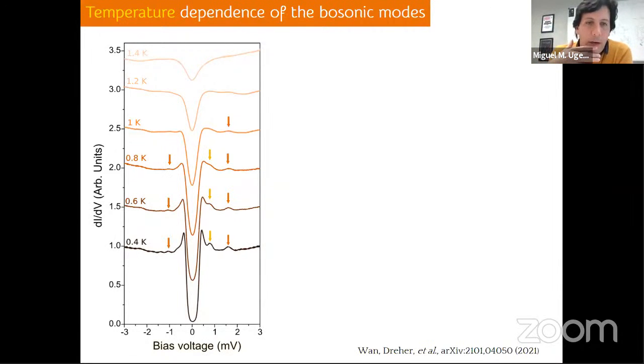So in order to learn more about the origin of these spin resonances, we have studied both the temperature dependence of these bosonic modes and the magnetic field dependence of the bosonic modes. Here I show you one typical set, increasing the temperature from our base temperature of 400 millikelvin up to 1.4 Kelvin. You can see here at very low temperatures, we can distinguish 3 different bosonic modes: the fundamental mode, which is here, and some replicas here and here. As you see, as we increase the temperature, still inside the critical temperature, these bosonic features decay. The amplitude of these bosonic features decays progressively and eventually dies, actually within the critical temperature. So before the critical temperature, which occurs at 2 Kelvin, we see no trace of these modes.